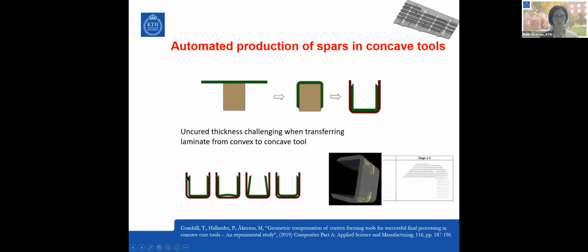So we looked at the possibility of having a gap, which is the way you have to do it. We looked at doing geometrical compensation of this forming tool, so that you had some excess length here that, after you cured it with a bag, you could press down and force the material towards the corners. We also looked at producing a forming geometry that looks like this, which made it easier to fit, with a different radius. And to see the material movement, we used some gold particles inside the lamina, and we used a CT X-ray machine to track it.